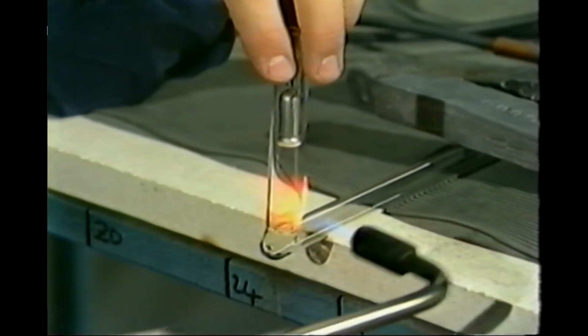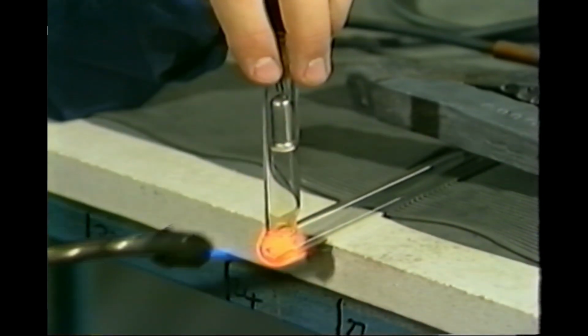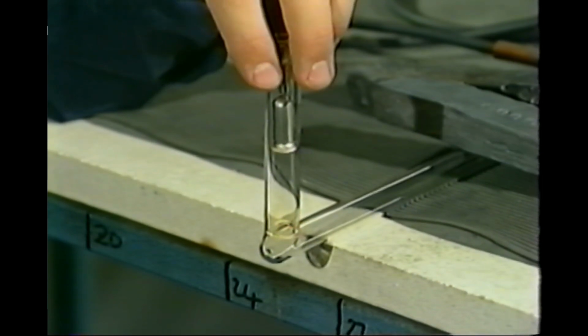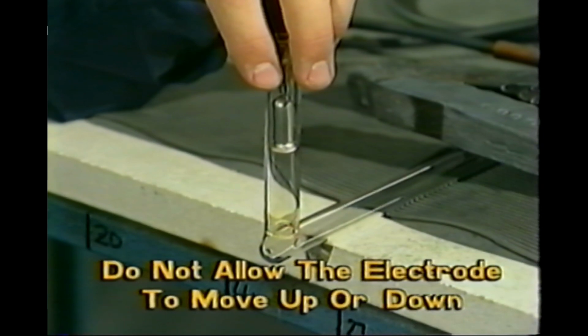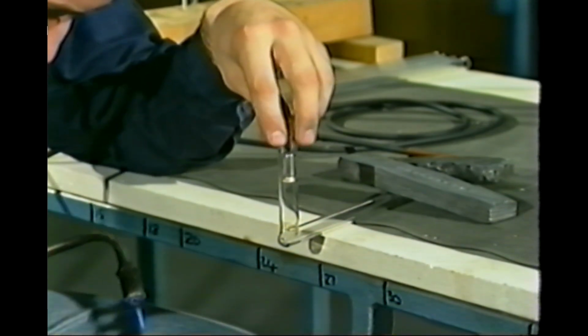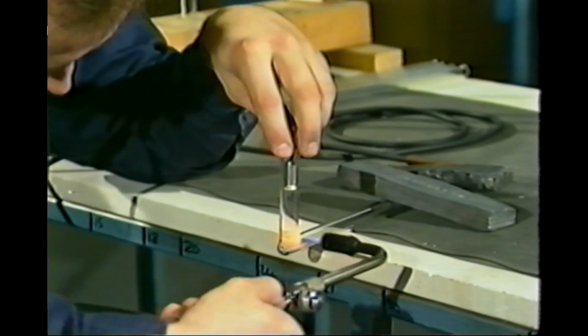At the end of this second melt, if successful, the joint will be clean and clear, with no ridges or folds visible. If this is not the case, a further melt and blow will be necessary. Remember, do not allow the electrode to move up or down during these melts. The final melt is performed the same as the previous ones.